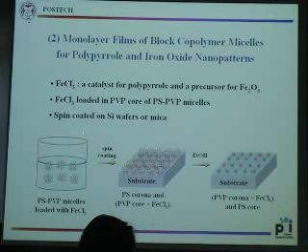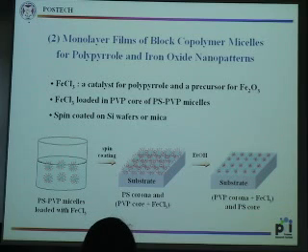conducting polymer case. Exactly the same as before, we spin-coated a monolayer film of PS-PVP micelles containing ferric chloride in the PVP core. And then we have the ferric chloride in the isolated phase. Then we treated them with ethanol to induce the core-corona inversion. So now we have the ferric chloride in the continuous phase.